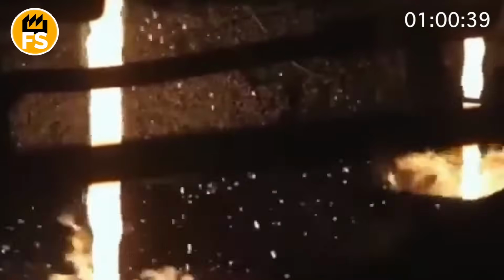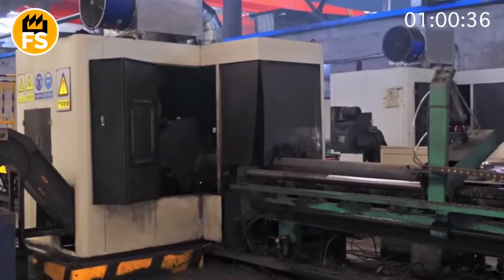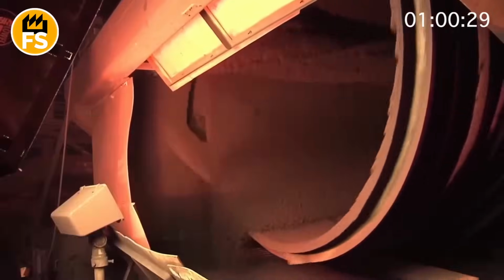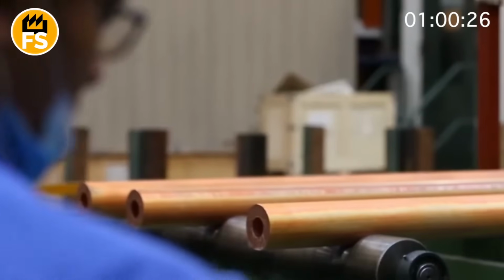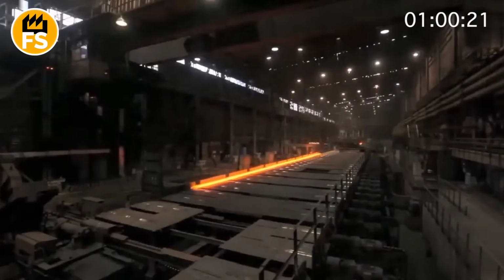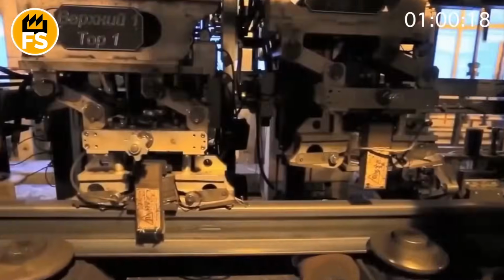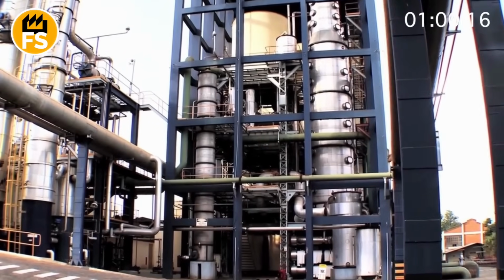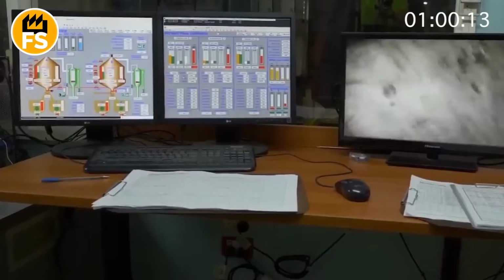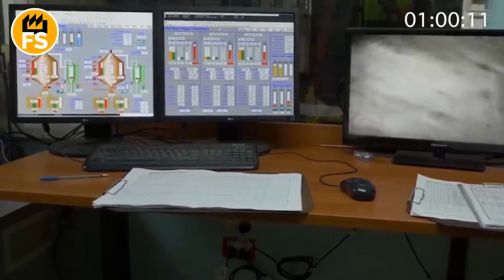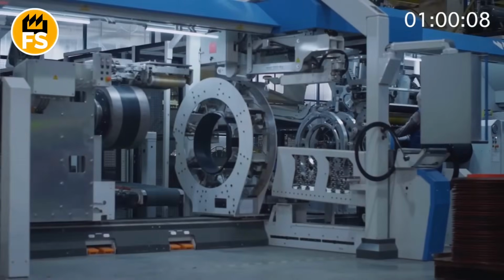The wire slowly passes through furnaces without an open flame, or through an induction field that heats it from the inside. The temperature, around 600 degrees Fahrenheit. This is the point where the metal doesn't melt, but changes its character. The atoms, which until now held onto their nodes in a stressed crystal lattice, finally relax. Like soldiers after a battle, like a string that has sounded at its maximum, and finally fallen silent. The metal structure becomes more uniform, the grains larger, and the wire itself flexible, elastic, calm.